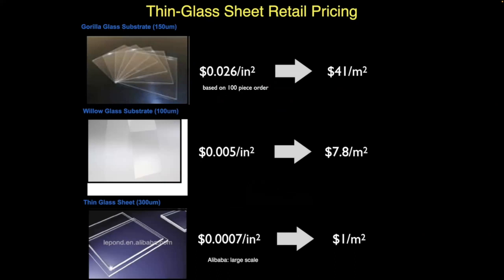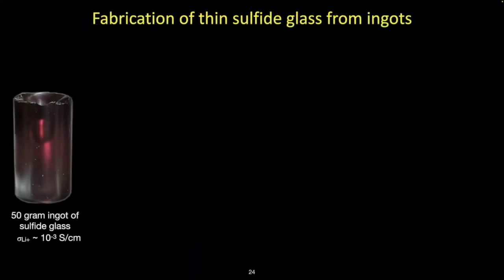So this is like a Google search. Let's look at the pricing of thin glass. Gorilla Glass, which is in your iPhone, just a retail order of 100 pieces, you're already at $40 a meter squared. Willow Glass, which is thinner, is roughly $8 a meter squared. And if you look at Chinese suppliers, you can get down to $1 a meter squared. So this is certainly the domain you want to be in if you're competing with lithium ion and need a path to get to parity.